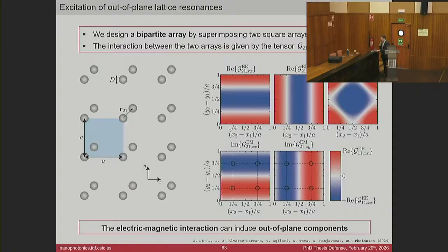Yes, this is something that the lattice resonance could be used for. First, you can think about adding a layer of some organic dye or something that you can strongly couple to your lattice resonance. And of course, if you add a layer, this is going to have a certain width, and you would like to have an excitation along the whole layer, let's say, not only in a tiny region like you will achieve with a localized surface plasmon. And also related to that, lattice resonances have been shown to be useful for coupling emitters that are relatively far away, because the lattice resonance can mediate this interaction.